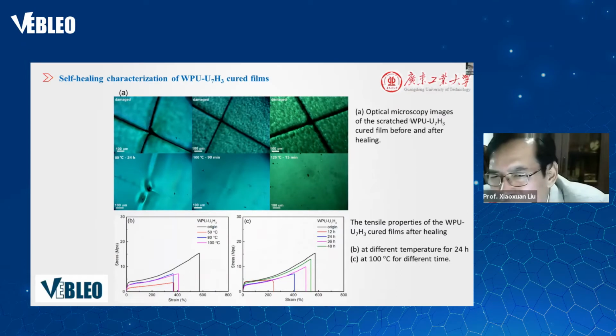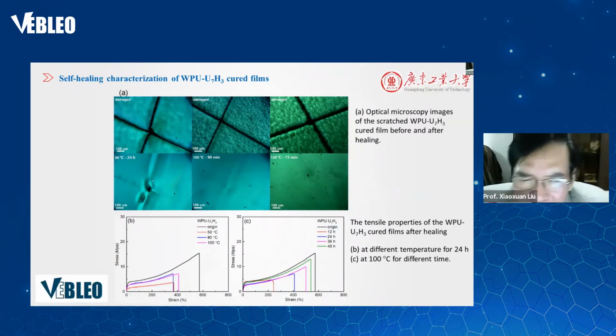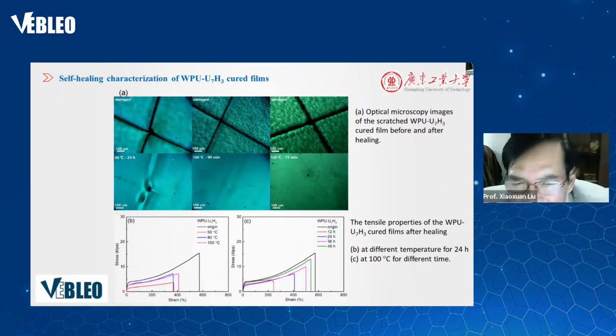The upper pictures are the optical microscopic images of the scratched and cured film before and after healing. This one is damaged and then heated at 80 degrees centigrade for 24 hours. This one is heated at 100 degrees centigrade for 90 minutes. And this one is heated at 120 degrees centigrade for 15 minutes. So at higher temperature, the healing time is shortened.